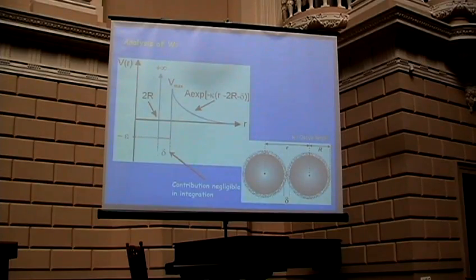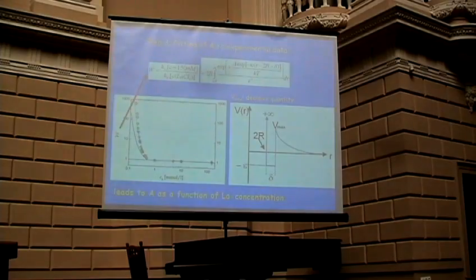The message of this picture is you measure K11 and you see here, the parameter is the salt concentration. You start out with a low salt concentration, and the slope of this curve is simply K11. If you go from 0.5 millimolar to 150 millimolar, there's virtually no change anymore. This means you have reached the diffusion-limited case. You give in more salt, it doesn't help, so diffusion is now limiting all the kinetics. From these numbers, you calculate the stability ratio, and we are really proud of these results because they give you a classical picture of the whole thing. First of all, you have the diffusion-limited regime. You can put in more salt, it doesn't help. The diffusion of the particles towards each other is the limiting factor. But then you have critical coagulation concentration. If you use less salt, the mountain to overcome becomes bigger and bigger, so the coagulation becomes slower and slower. Here, in the final state, the particles are coagulating by a factor of a thousand slower than the diffusion-limited case. This is a double logarithmic diagram. You can go over the stability ratio for three orders of magnitude and explore very precisely the repulsive force.